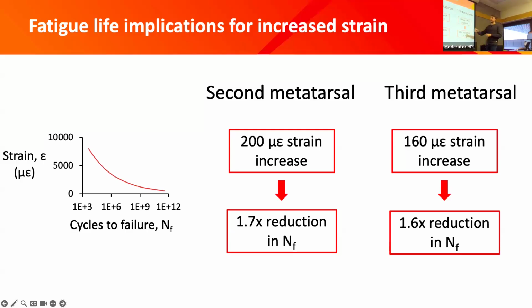And what we can see is that the 200 microstrain increase that we see when we go from the intact plate to the cut plate condition in the second metatarsal corresponds to a 1.7-fold reduction in the number of cycles to failure. So that's a 1.7-fold reduction in number of cycles to failure from that 200 microstrain increase. Same thing for the third metatarsal, although the strain increase that we observed from the intact plate to the cut plate shoe is slightly smaller, so it's only 160 microstrain, and that corresponded to about a 1.6-fold reduction in the number of cycles to failure there.